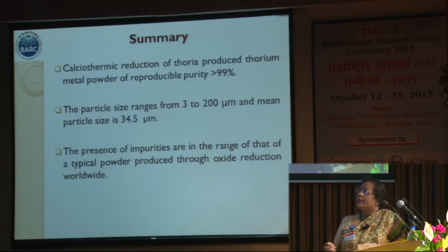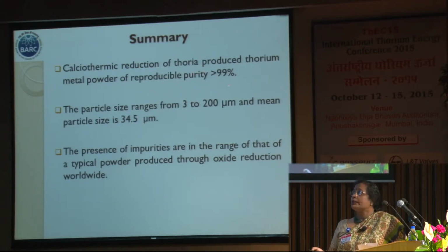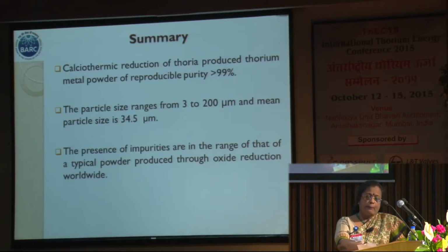So calciothermic reduction of thoria produced thorium metal powder with reproducible purity of more than 99%. The particle size ranges from 3 to 200 micron with a mean particle size of 34.5 micron. And the impurities are in the range of typical powder produced through oxide reduction worldwide.